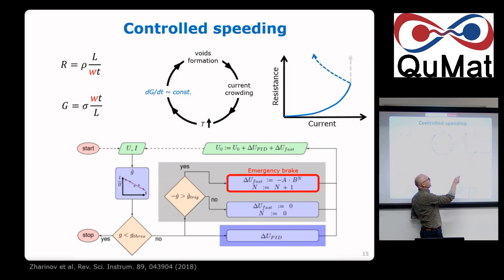But the point is, once we get to this point, if we see that the system wants to explode, we reduce the current. Okay? And it's a fight between the system and our software. The system is trying to explode and you don't want that, it's like Chernobyl, and if you don't do it well, it explodes. Okay? So we build up going through this curve, but it's a fight. It's really a fight. So you don't go smoothly. You go like tick, tick, tick, tick. Okay? And in that way, we can go up in the resistance of the system.